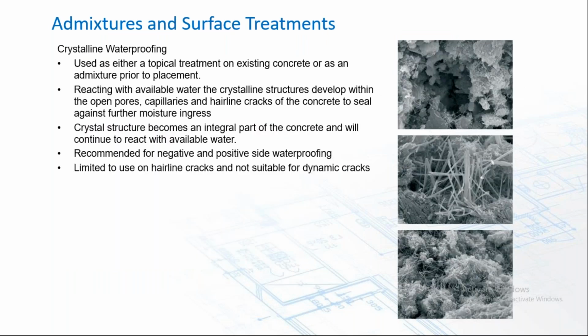So crystalline waterproofing can be employed either as an admixture or as a surface treatment. These chemicals react with the available water, and crystalline structures develop within the open pores and capillaries and hairline cracks of the concrete to seal against further moisture ingress. Understanding that concrete is full of pores and capillaries, this now creates an additional growth of these crystalline structures to prevent moisture ingress. It becomes an integral part of the concrete and will continue to react with available water.